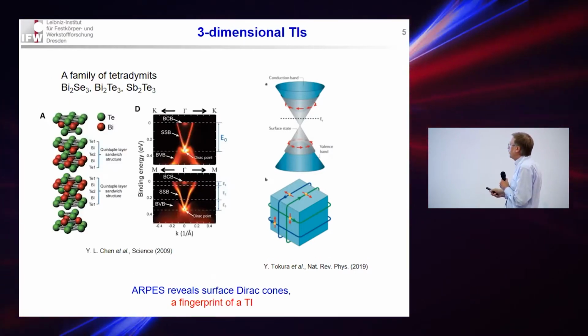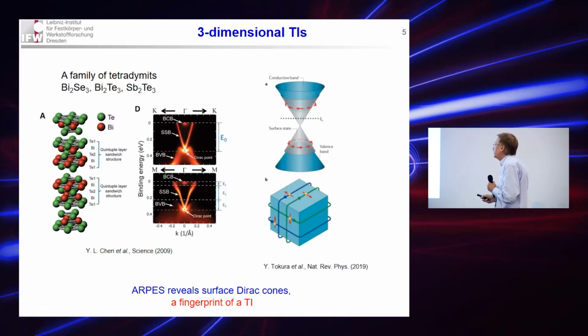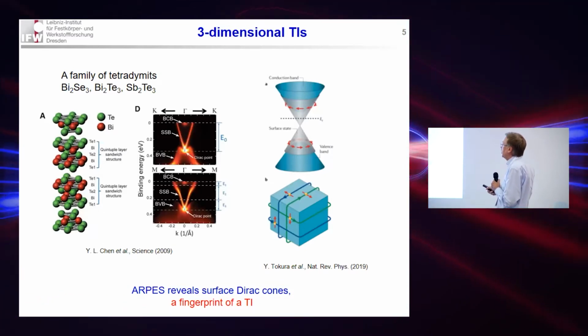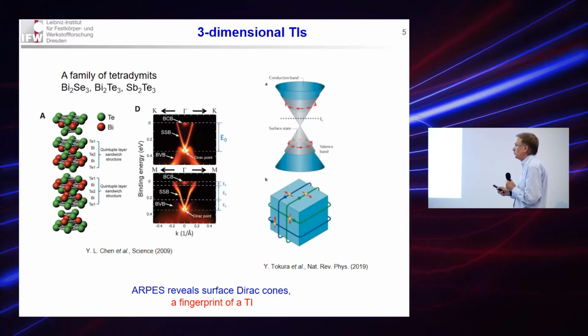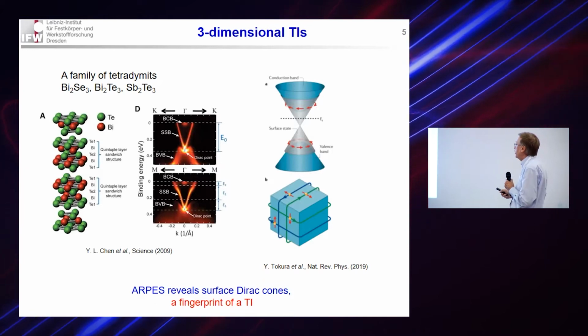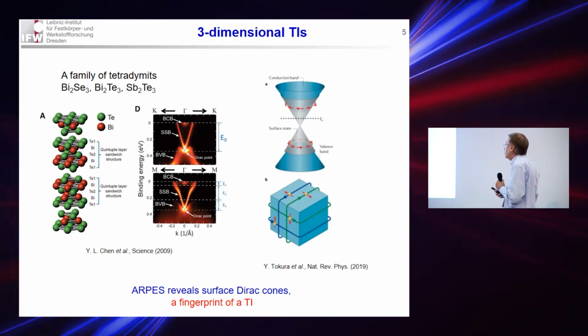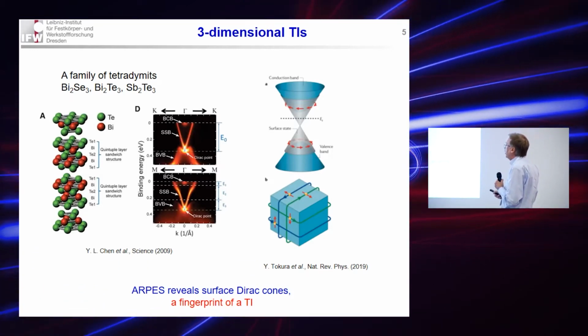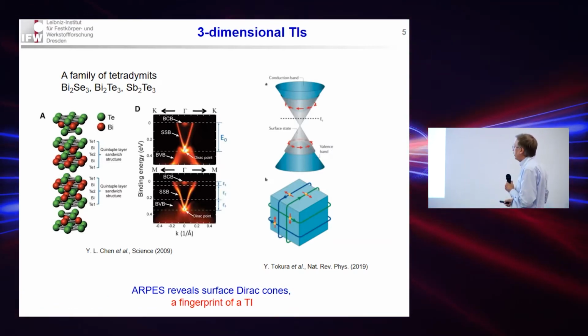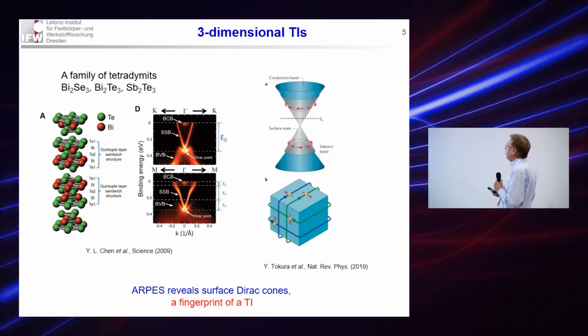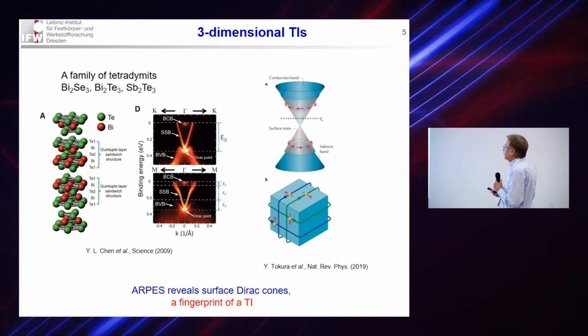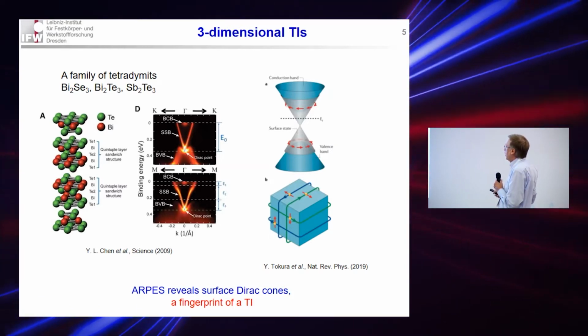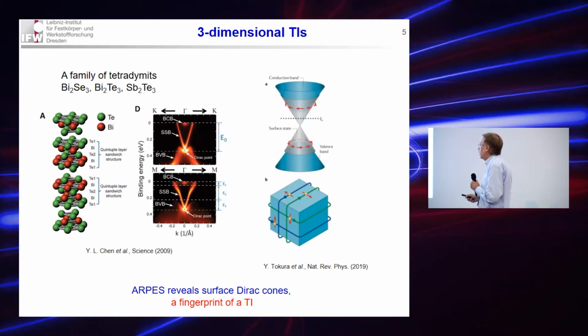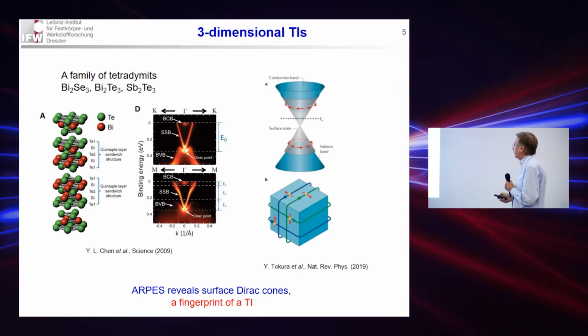Like, for instance, a very famous family of tetradymites. These are compounds containing heavy metals with strong spin-orbit coupling: bismuth selenide, bismuth telluride, antimony telluride, and so on, where indeed experimentally, in angle-resolved photoemission spectroscopy, evidence for surface states linearly dispersing in momentum was found.